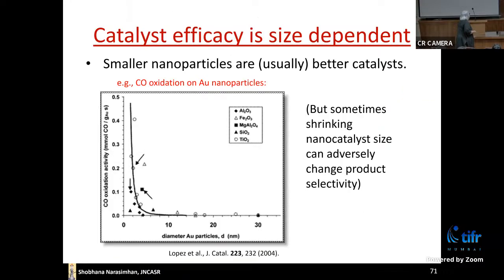So if you look, for example, at this reaction of carbon monoxide oxidation, and you see how well it proceeds versus the diameter of the gold particles, you see it, as the particle diameter becomes smaller and smaller, it's faster and faster. So you really want your gold nanoparticles to be small. You don't want them to join together and form bigger and bigger nanoparticles. But this is what happens in practice. So this sintering is the biggest cause of catalyst degradation. It spoils your catalyst.